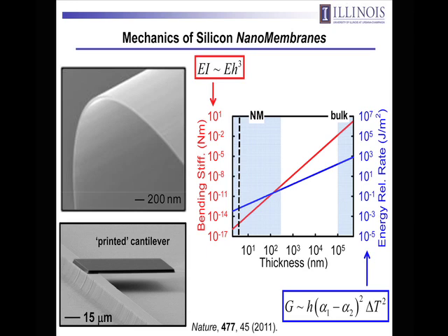So if you look at basic fracture mechanics, you can derive expressions like this. This corresponds to fracture induced by a difference in thermal expansion coefficient of this silicon plate and the underlying substrate, which could be a sheet of plastic. Those two materials have much different CTEs, and so if you heat them up, interface stresses will tend to drive a crack at that interface. But the energy release rate is actually linearly proportional to the thickness of the plate that's sitting on the substrate.